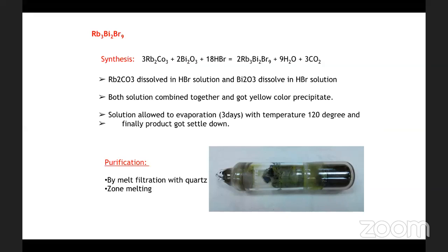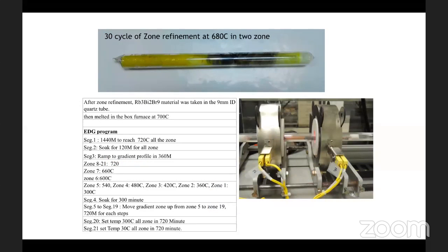And this work I have done at Argonne National Laboratory in the US, where I have grown rubidium bismuth bromide. Basically, this material is prepared by solution growth. Once you prepare the material by the solution method, we dried it completely for 3 days, and then we put it in a quartz crucible and filtered it. Then we got some material, and that material we purified using the zone refinement method.